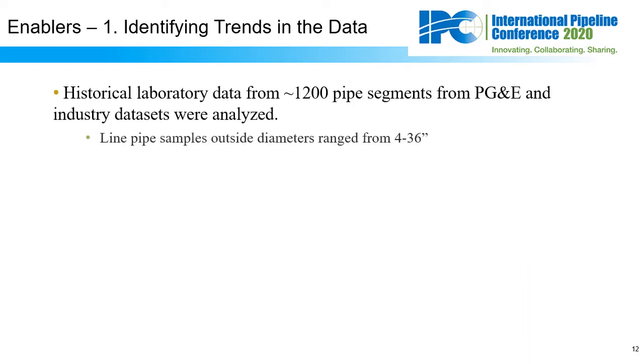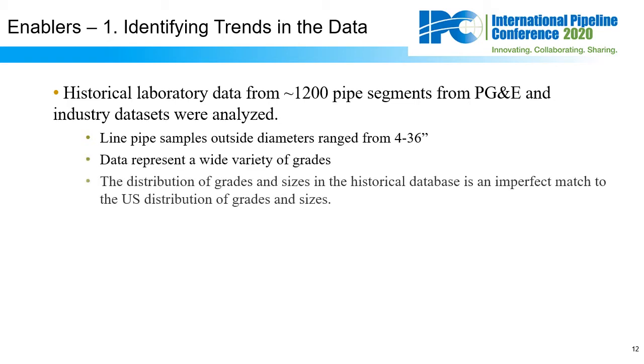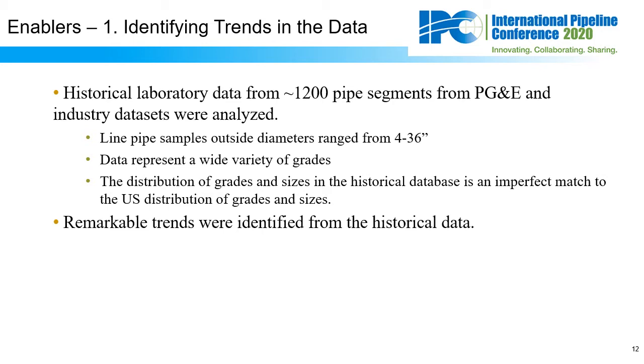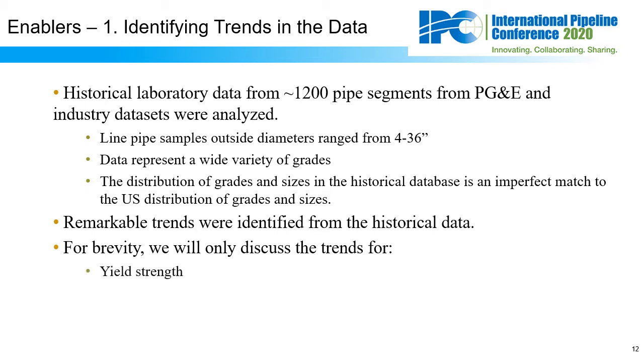Firstly, in terms of enablers, our database of historical line pipe test results came from about 1,200 pipe segments from PG&E and industry data sets from a wide variety of pipe sizes. We were able to identify interesting trends in the data in the strength and composition by plotting the data over time. For brevity, we're only going to discuss the historical trends for yield strength, manganese, and sulfur.